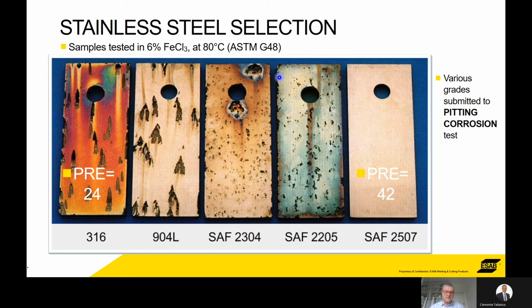You can see it's been affected, it's been corroded on all surfaces, and we've got the start of pits all over the surface. So compare that with SAF 2507. This is a super duplex with a PRE of 42. You can see it's been exposed for the same amount of time, same temperature as the rest of the test coupons, and it looks like it's not been touched. So that's a good illustration as to why duplexes were developed. You have fantastic strength and excellent corrosion resistance.